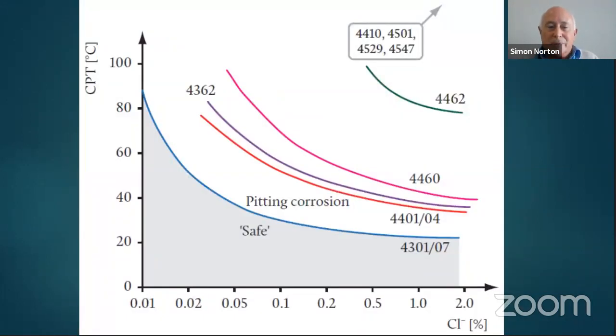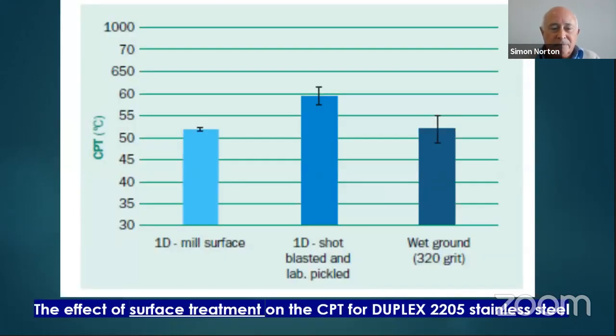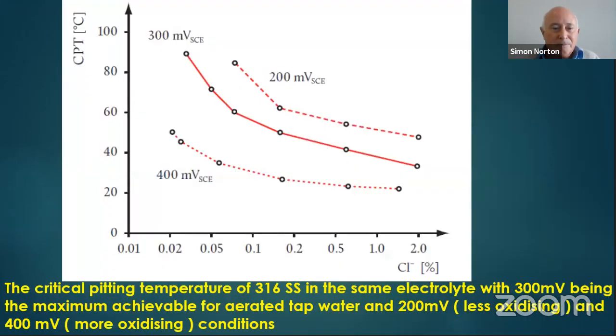And if you look at this chart that I'm showing you here, you will see that on the left-hand side is critical pitting temperature, and on the bottom axis is the chloride content. And from these sorts of charts, you can work out where to use your stainless steel. Here again, you can see that different surface finishes have resulted in different critical pitting temperatures for duplex 2205 stainless steel. And again here, you can vary the response of your material by examining the critical pitting temperature.